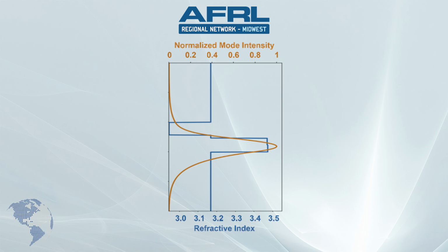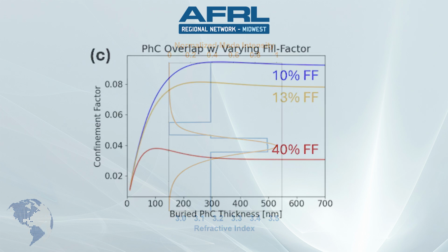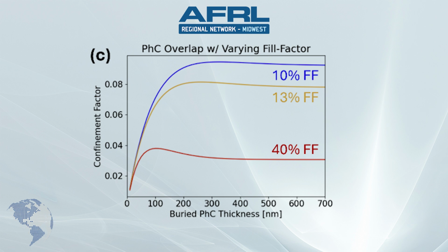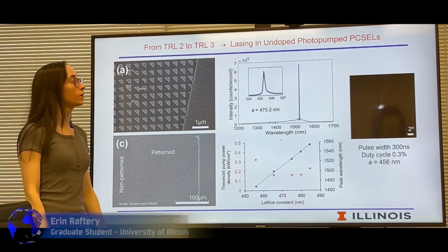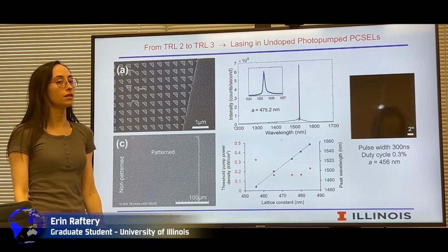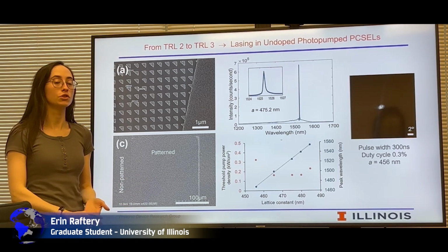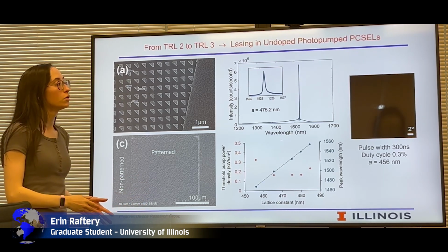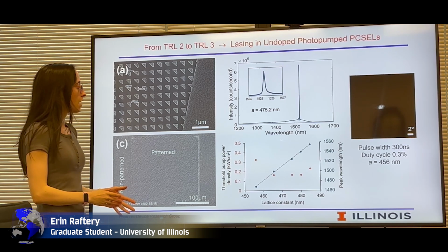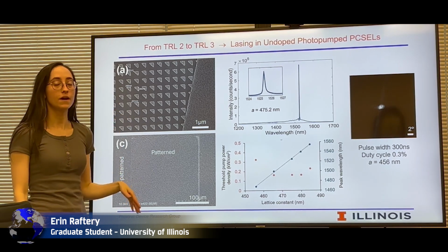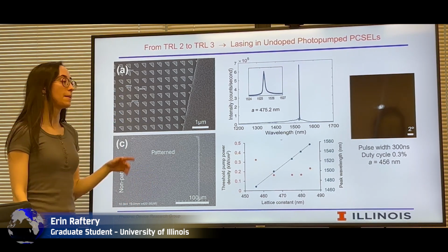And so we found, compared to literature, we think we need to be at least above 7% overlap with the photonic crystal region. So we fabricated devices with 13% and also 10% fill factor SiO2. So in the second increment, we have increased the TRL level from 2 to 3 by demonstrating lasing in the undoped photopumped PCSELs. So we did decrease the fill factors to 13% and 10%.